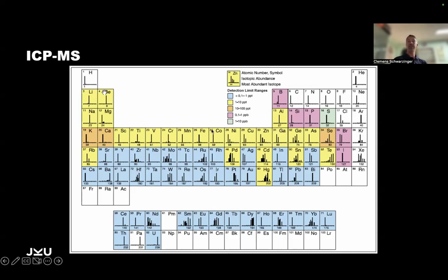Mostly of interest are the things here in this top range, the yellow ones and the blue ones. What does the color indicate? The color indicates how precise we can measure them. Like the blue ones, you see it here below 0.1 to 1 ppt. Now, what does ppt stand for? Parts per trillion. You see parts per million is 1 in a million. Parts per billion, this is like sulfur here, or the red ones, we can measure them down to 1 part per billion, and then we go down to 1 part per trillion. So this is a very, very sensitive machine, which is necessary because sometimes we need to differentiate between 1 ppm there or not there.